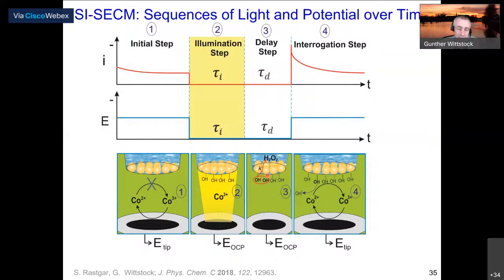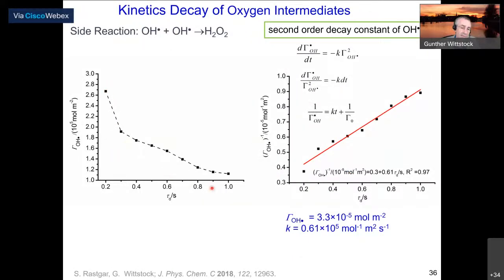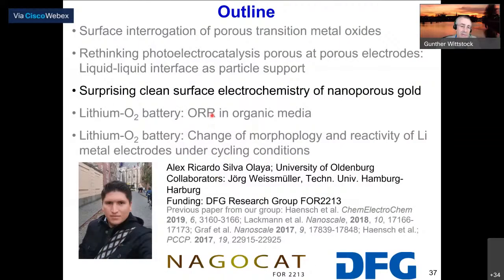And these particles can make oxygen evolution. The intermediate is an adsorbed hydroxyl radical, and two of them can combine to form hydrogen peroxide, or can be desorbed. So we allow that reaction to proceed, and then we titrate the remaining hydroxyl radicals. And again, as a function of the waiting time, we see a decrease in the surface concentration of the intermediates. We can fit that to a rate law and extract rate constants from that. Again, that's a very interesting and also very new concept for the reaction, but also a method to address those surface properties.